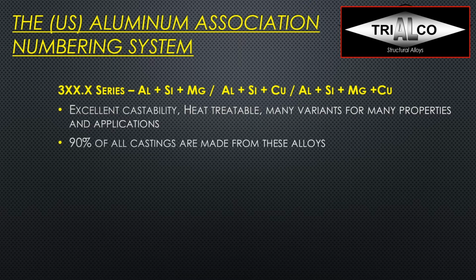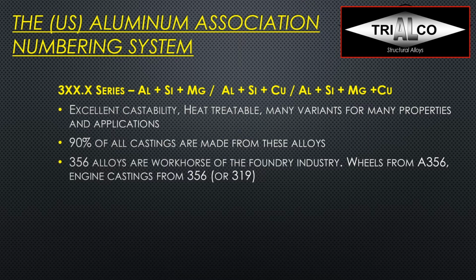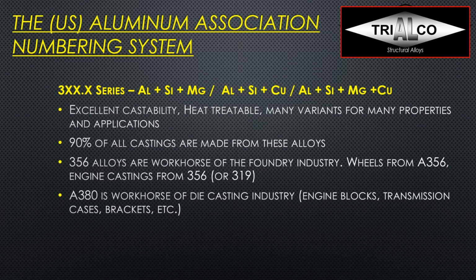And that series covers pretty much 90% of all castings made in North America. The 356 alloys are the workhorse of the foundry industry, and as you probably know, wheels are made from A356, so a relatively high purity, basically primary version of it, and engine castings are mainly made from the secondary 356 or the 319. A380 is the workhorse of the die casting industry, so you could say that's the most common foundry alloy in North America, but basically worldwide, with slight variances in other regions of the world, but it's basically the alloy that's made from 100% recycled content.